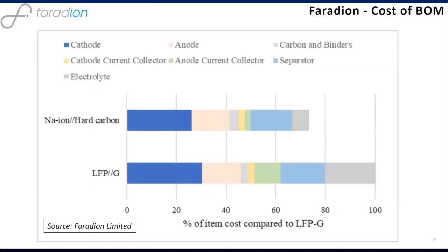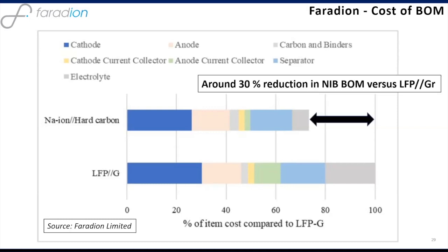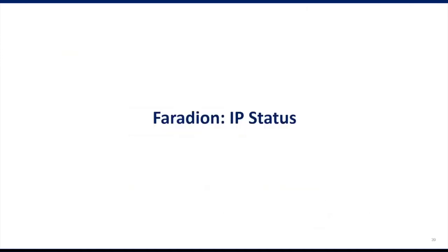Cost analysis: we keep this under constant review, and we compare ourselves at Faradion with the best that commercial LFP graphite can do. Obviously this is a moving target, things are changing all the time. As I said earlier, the cost of the lithium precursors going up is actually working to our advantage. Right now, we are suggesting that for energy cells against commercial LFP graphite, we're around 30% less in bill of materials in terms of dollars per kilowatt hour than the lithium iron phosphate graphite. So that's a very handy saving.